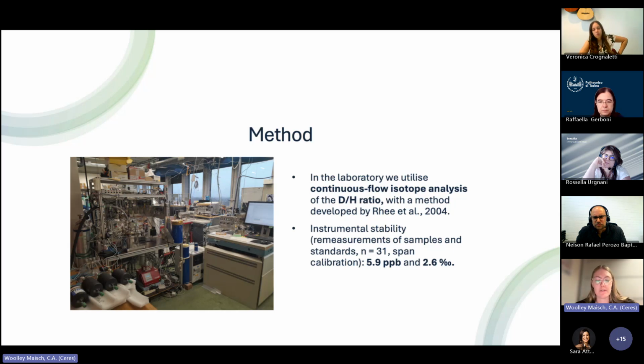And as I mentioned, I think at the moment it's the only system that can measure background samples of hydrogen for the delta D signature. And that's really valuable because then we can measure downwind of the source. We don't need to have pure samples. We can just go outside the fence line. We find the plume. Normally we have the Aerodyne instrument with us, and then we collect the sample. And this was developed by Rhee et al. in 2004. And as I mentioned, we restarted the instrument in the last year. And since then we have an instrument stability of around 5.9 ppb and 2.6 per mil.